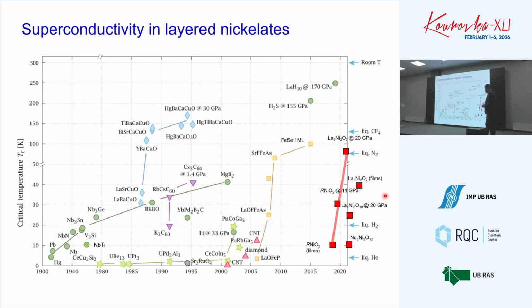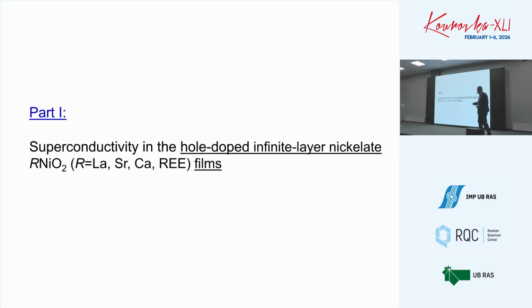Nowadays, the most focus is a switch from thin film phases to bulk. People try to stabilize superconductivity at ambient pressure. And there are some claims about superconductivity with relatively high TC, like 40 or 50 K, but with no external pressure. Okay, my first part is about infinite layer nickelates.